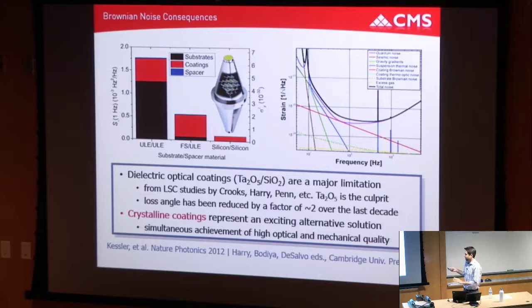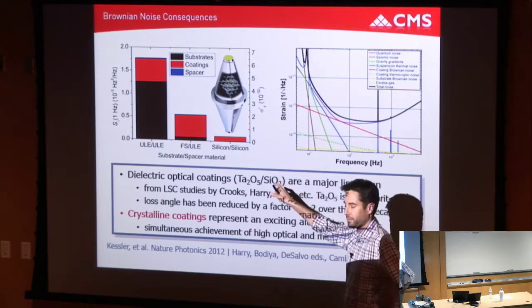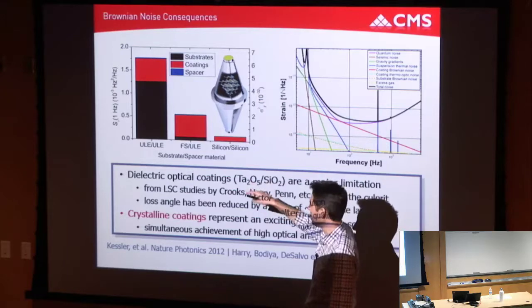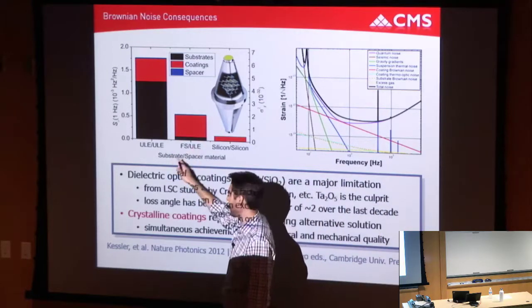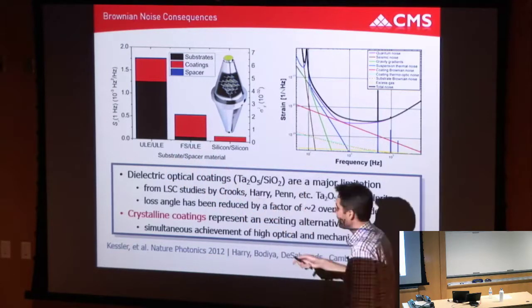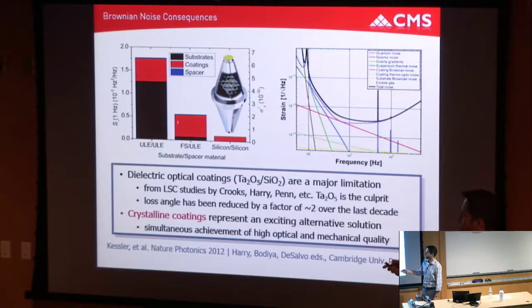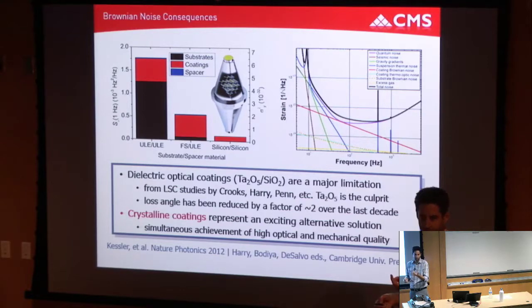If you look at the actual consequences, these are busy plots, so I'll walk through it. This is an interesting plot from a paper by Thomas Kessler from PTB. This is total noise of a reference cavity as a function of material selection. All the early cavities were made from ultra-low expansion glass, with the thought being that, well, I'm going to have finite temperature control in the system, so I want zero expansion of every component of that cavity. But then this work by Saulson, and then applied by Kenji Numata from NASA Goddard, showed what you really want to do is increase the mechanical quality factor.